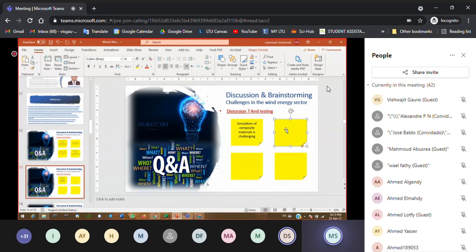We actually, in that project, especially for the 25-meter long blade, did not measure the shrinkage after the fabrication process, but we experienced that shrinkage because we're using epoxy. And epoxy, I think the shrinkage exceeds that of the polyester, as far as I remember. And yes, after the infusion of the two halves of the blade, we started to see separation of the part from the mold. So yes, we experienced some of this shrinkage.